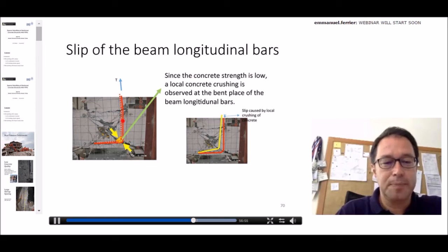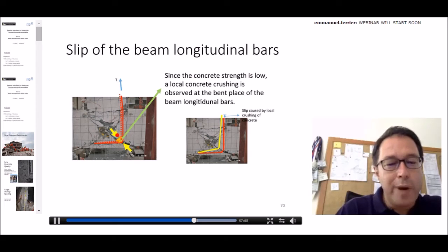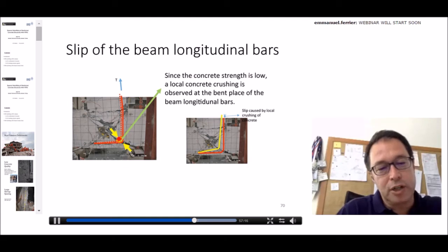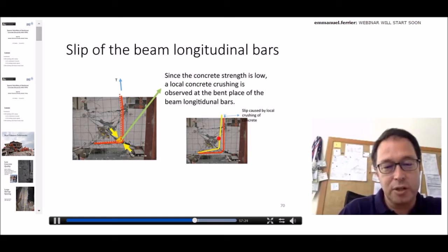When we apply tension to the top bars during lateral loading, we have quite high concentrated stresses just around the hook, which cause crushing of concrete around this area. Because of the gradual crushing of concrete here, the shape of the longitudinal bar, which was hooked 90 degrees, changed, like the yellow one. And obviously, this caused slip, or displacement, of the main bar.